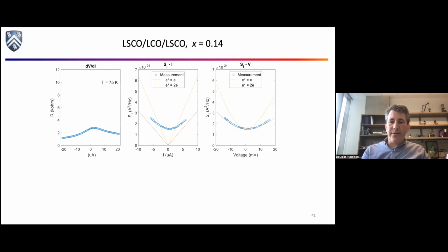So let's cool down. And as we start cooling, you can see this thing gets more and more nonlinear, more non-ohmic. And notice, even here we are at 65 K, 25 degrees or so above the superconducting transition. And already, if you look closely, these blue data points are lying above the red line. There's more noise than you'd expect for just single electrons tunneling by themselves.